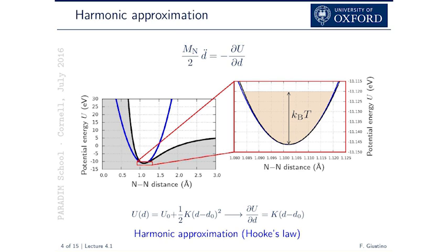So in practice, for calculation, what we do is go to MATLAB or gnuplot and fit a parabola in this range to this object. So my potential energy surface is equal to some constant, which gives me the baseline, plus a coefficient times the variable to the power of 2. There is no linear term because it's a minimum, so the first derivative is 0. That's a way of proceeding, and these two numbers come from a fit. So we first do our DFT calculation, then we do a fit, and we obtain that.